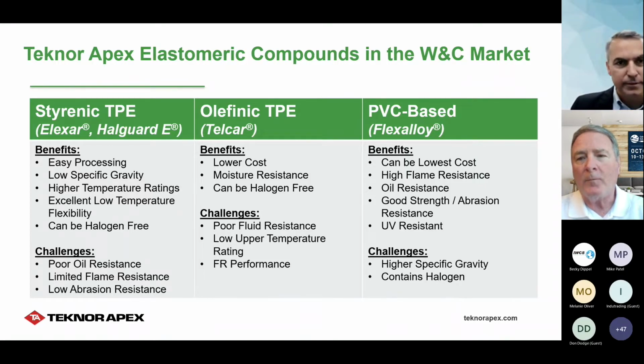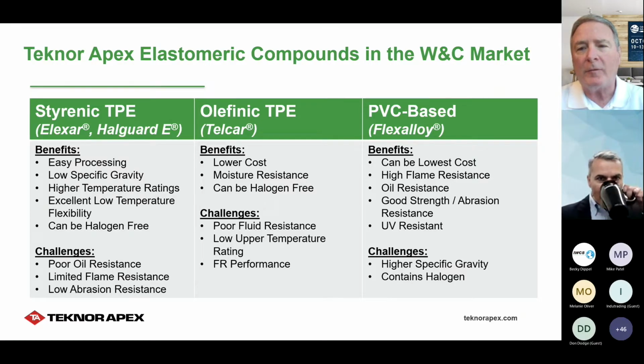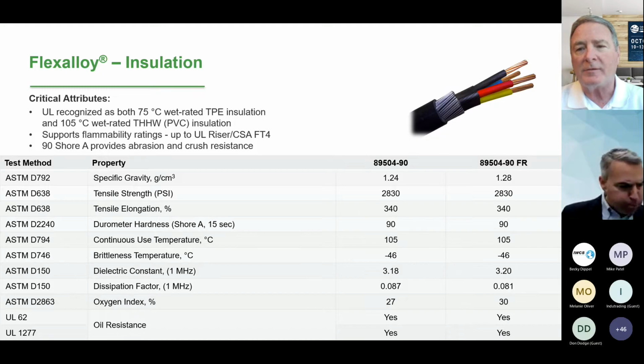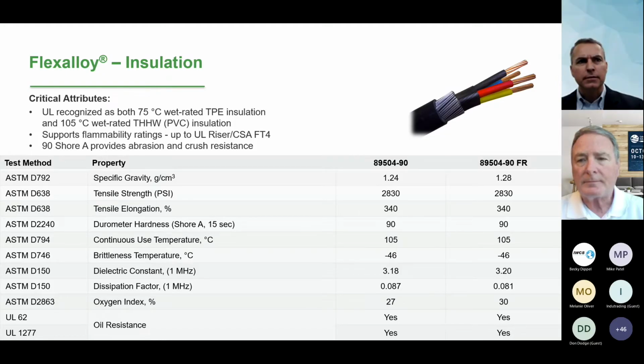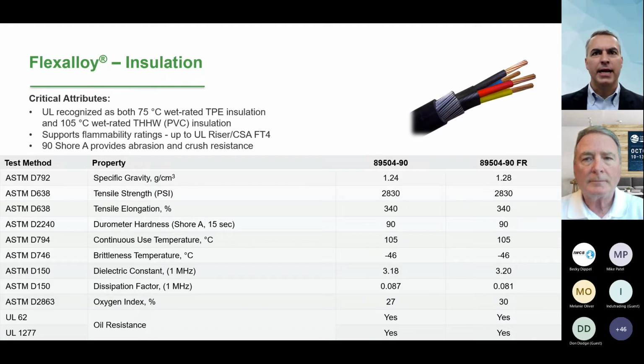Very good. Will the 89504 material be flexible enough with a 90 durometer hardness? Yeah, so it is. Typically cable designers formulate with the insulation, which is a thinner layer, being a bit harder to protect the conductors and the jacket being a softer layer. A 90 hardness doesn't mean that it's going to crack when you bend it, far from it. It just means that it's a little stiffer as you bend it.